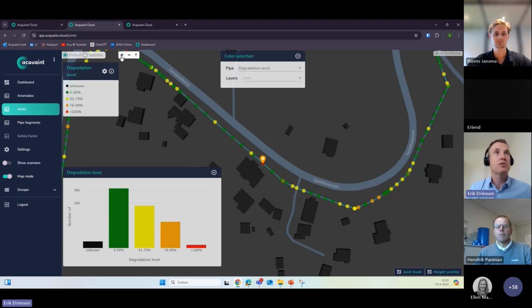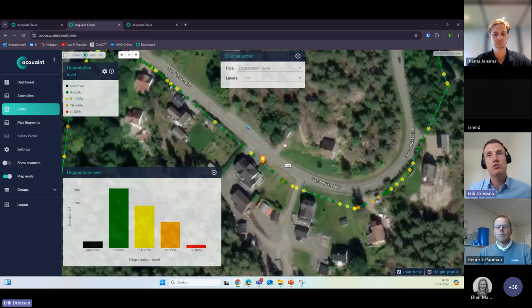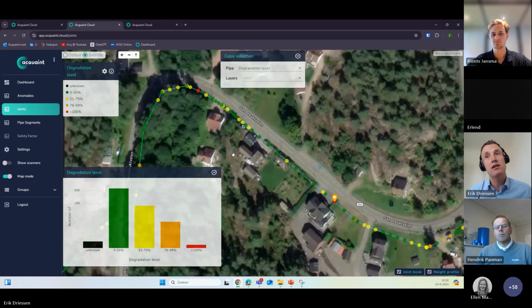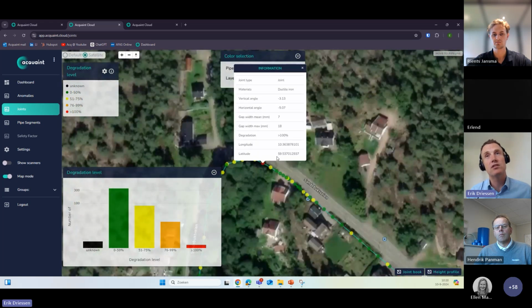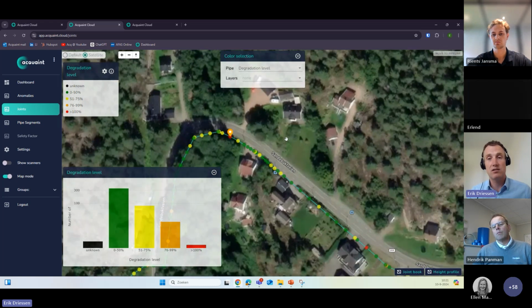So what often also helps is when you enable the satellite view here, you see where does this joint sit, and sometimes you see a dirt road going over it with heavy traffic, for example, which is not the case in this situation. And when I go a little bit further, you see another red joint here, which has an horizontal angular displacement, but also a vertical and also a gap width, maximum 18 millimeters. So these are also the joints that Riens just showed in the PDF report, because we would like to help the client to look at the most concerning items that we have spotted.